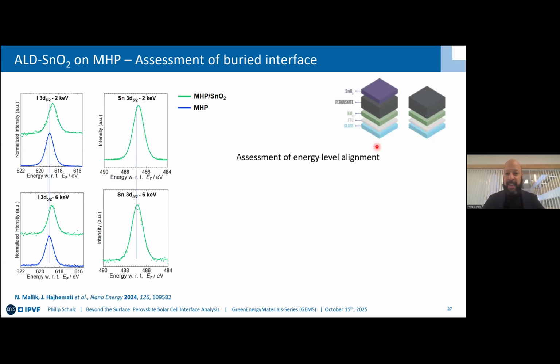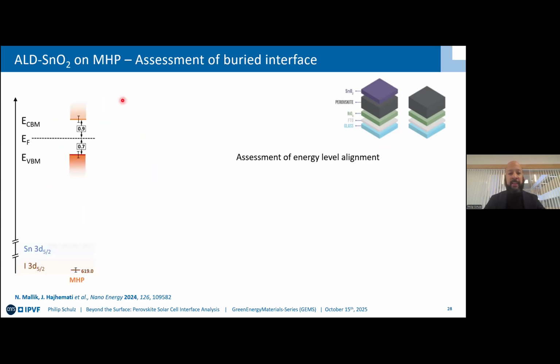Can we still assess the energy level alignment? One can at least try, and we do this by identifying peak shifts. Note that everything is always referenced to the Fermi level of the device. So by looking into peak shifts from 2 keV to 6 keV, we can see that the tin oxide is shifting, or elements in the tin oxide, but so also are the elements in the perovskite. Except for the pure perovskite, not really. But once you go to the system with the tin oxide, you can clearly manifest these shifts.